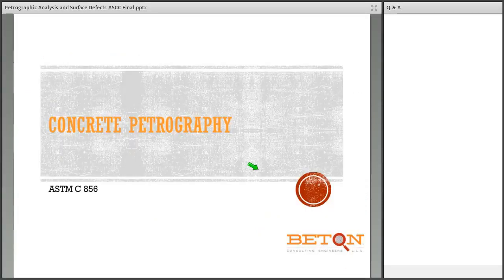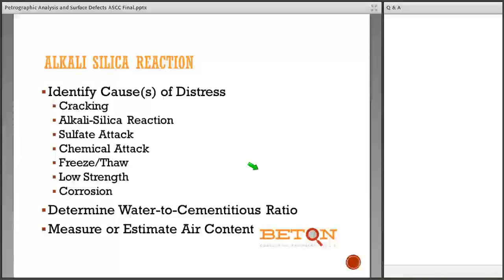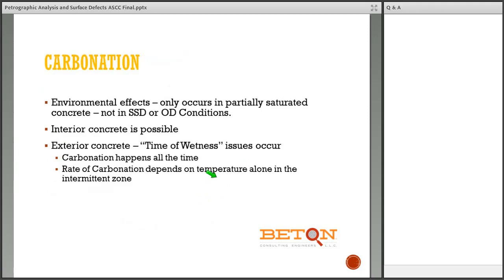Okay, and we'll talk a little bit about concrete petrography, ASTM C856. Previously, we were just talking about the aggregates. We use concrete petrography to identify the causes of distress, like cracking, alkali-silica reaction, sulfate attack, chemical attack, freeze-thaw damage, low strength issues, and corrosion, especially spalling due to corrosion. Determine water cementitious ratio, and measure or estimate the hardened air content. I'll skip past this one. That was a kind of duplicate slide.